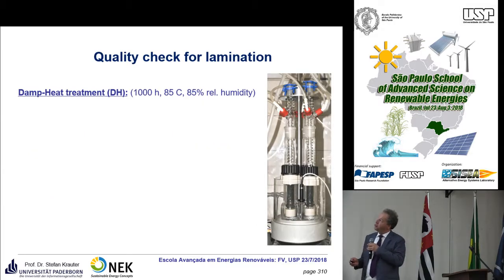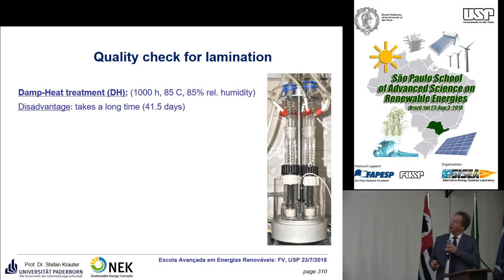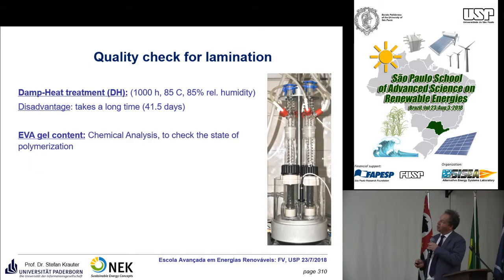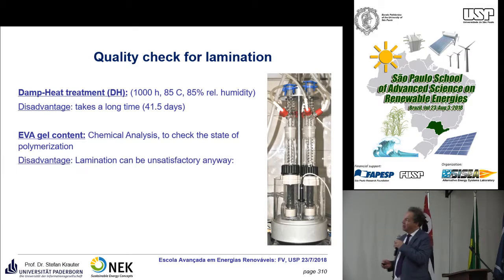Quality checks for lamination: you can do the damp heat treatment, but the problem is it takes 1,000 hours. So it takes 1.5 months until you get the results at least. So this is not much. What you can do is a chemical analysis to check the state of polymerization of the EVA.